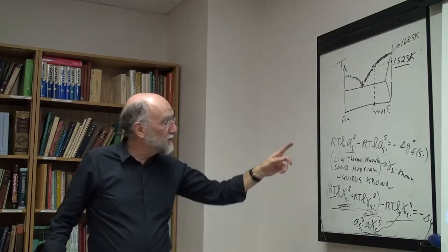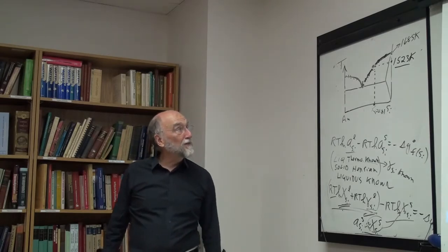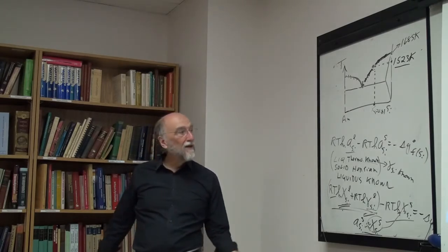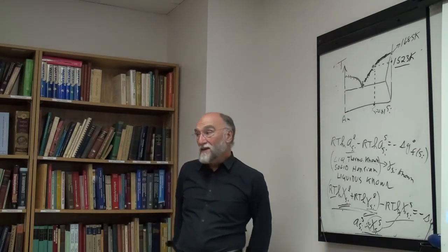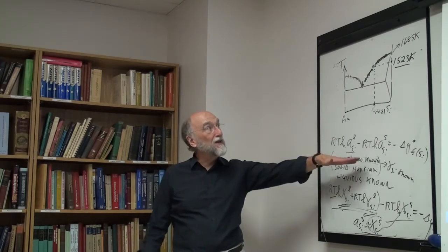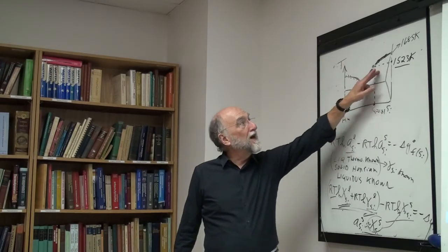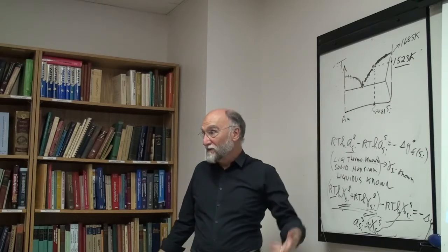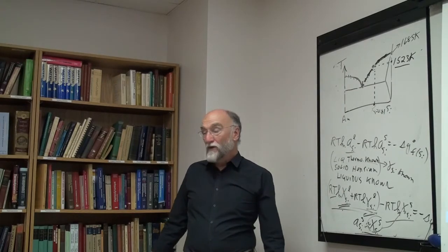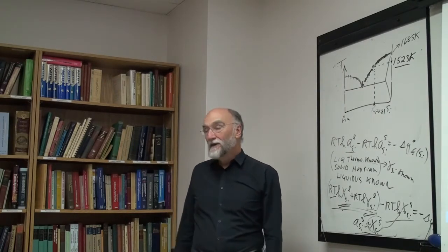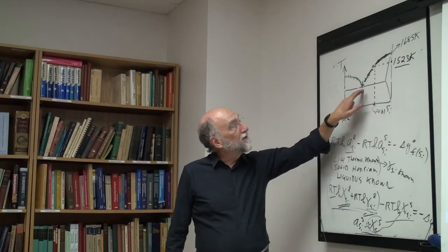Okay, so this is a useful calculation which you can do very quickly sometimes, just to get an order of magnitude idea of the solid solubility. This is not going to give it to you exactly, but certainly 0.99 will be different from 0.85 or something. You can find out pretty quickly whether it's a good assumption or not, and maybe even that the eutectic would be even more.